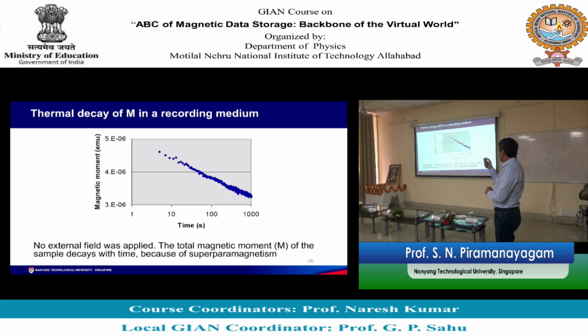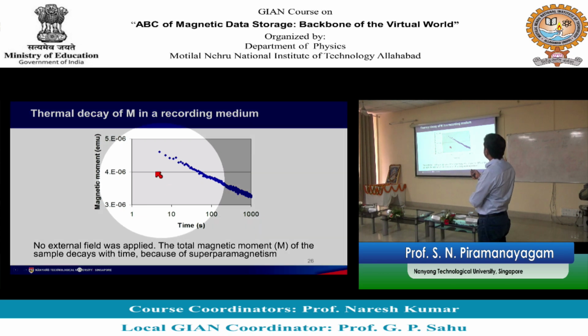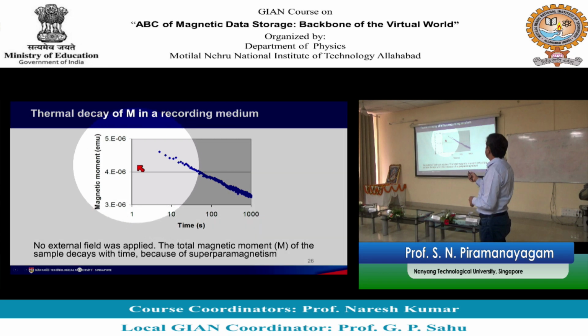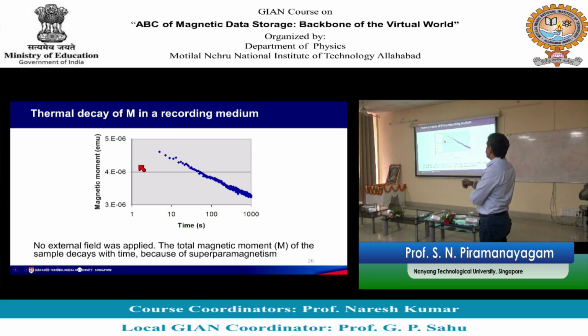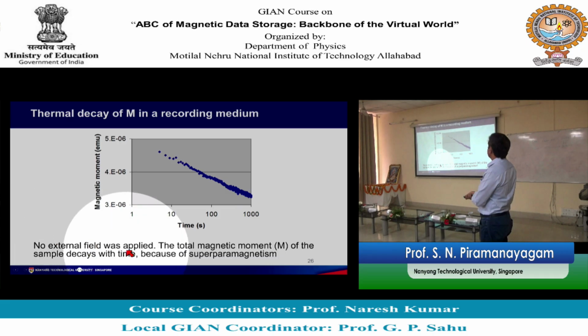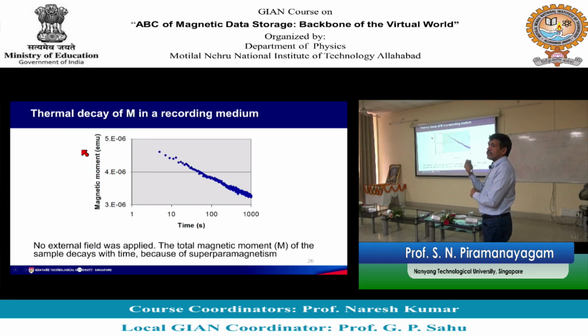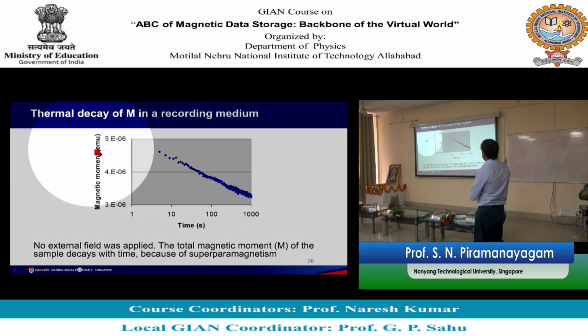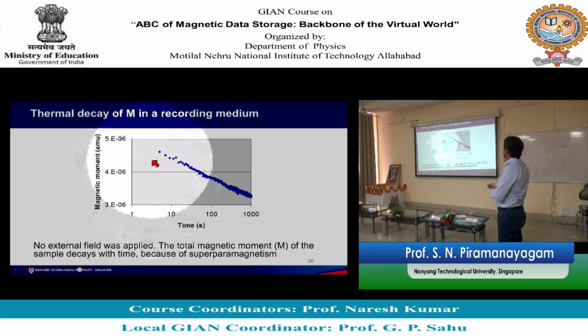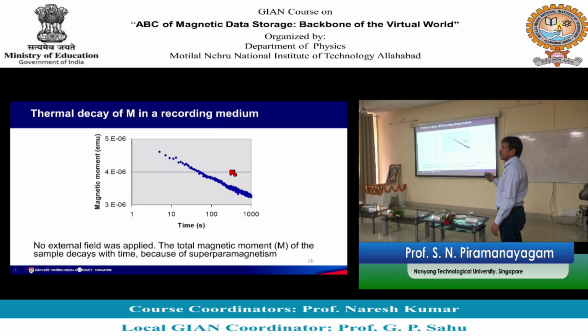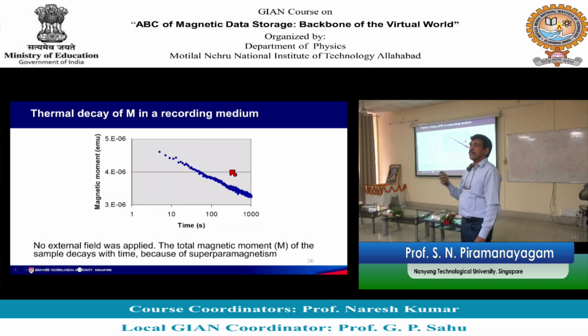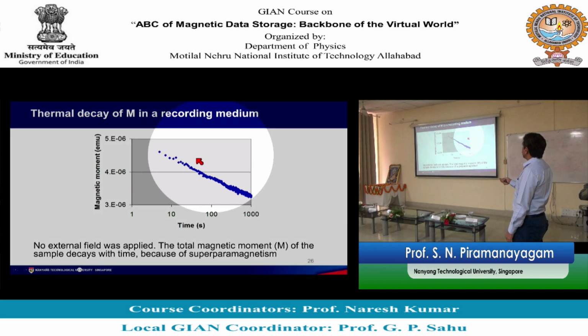So, here is one sample that I measured. I keep a piece of recording medium in the VSM, I saturate with a certain field, and remove the magnetic field. So, no external magnetic field. I am observing the magnetization of the sample as a function of time. I notice that the magnetization keeps dropping as a function of time. We are not doing anything, we are just observing, and the magnetic moment of the sample just keeps dropping as a function of time.